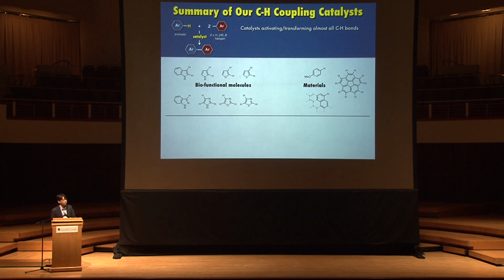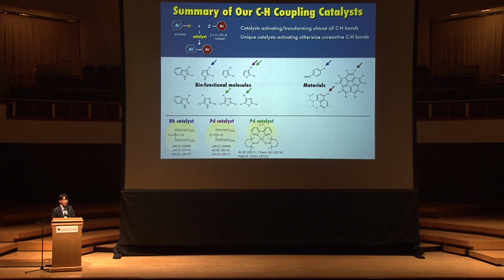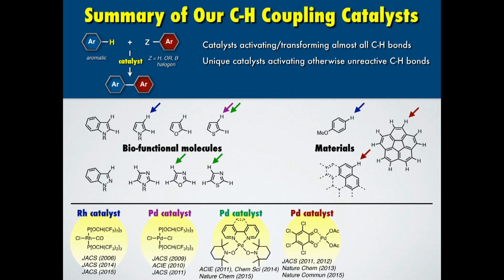So for the last 10 years, we were able to develop catalysts activating and transforming almost all CH bonds, shown here, by catalyst control, not by directing groups. But more importantly, we were able to develop unique catalysts activating otherwise unreactive CH bonds that are highlighted in color, by unique rhodium or palladium-based catalysts. For example, it is not easy to hit the beta position of pyrroles or thiophene, but our catalyst can do that. So this is the power of catalysts.